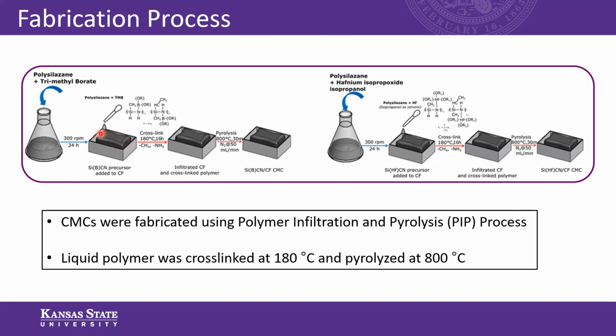So this object here would represent the carbon fiber that is being coated. These were cross-linked in that same argon atmosphere at 180 degrees Celsius. And then in a tube furnace with nitrogen atmosphere, the samples were pyrolyzed to achieve the final ceramic state of the CMCs. Samples were coated with 3 drops, or approximately 60 microliters per each sample.